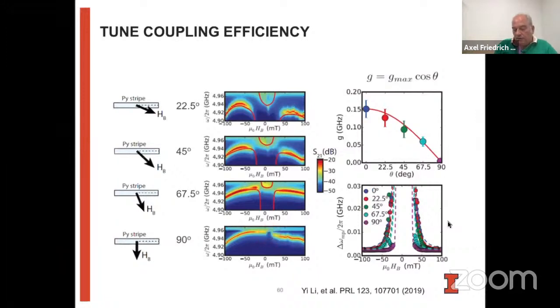And the reason is, of course, that at the center, there's no field anymore to saturate the permalloy stripe perpendicular, and the magnetization will rotate back to be along the stripe. And you do get a little bit of coupling here that leads to this gap in the excitation. But if we now plot the coupling strength as a function of this angle of the orientation of the magnetic field, we'll see that it follows very much a cosine kind of behavior, as you would expect from the geometry of the coupling.